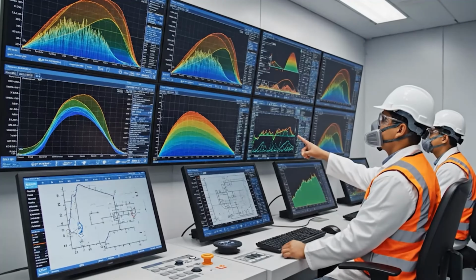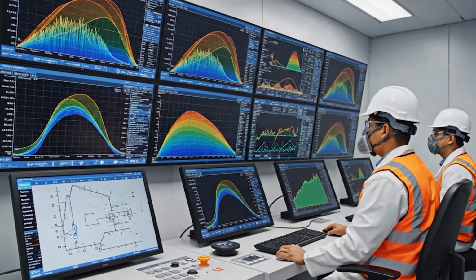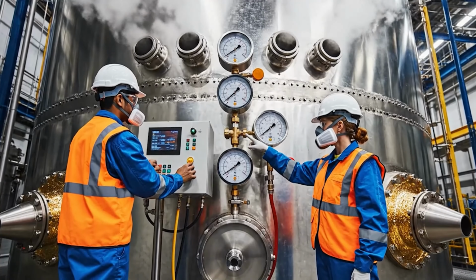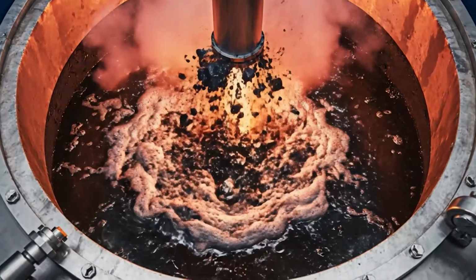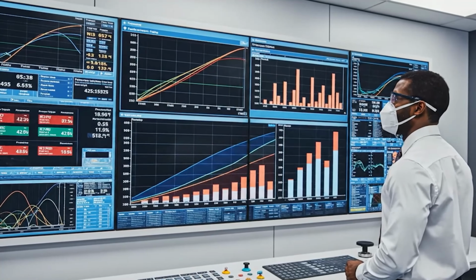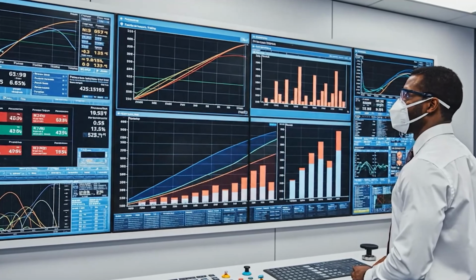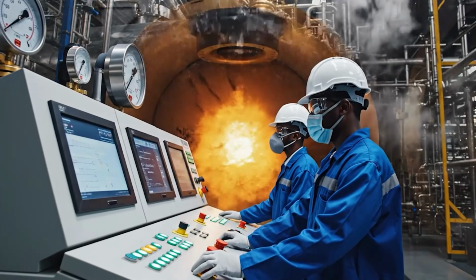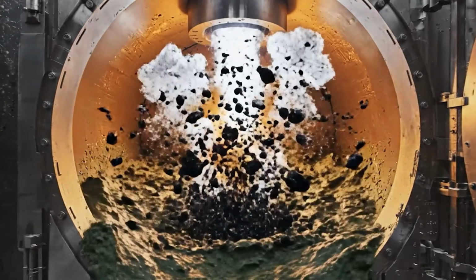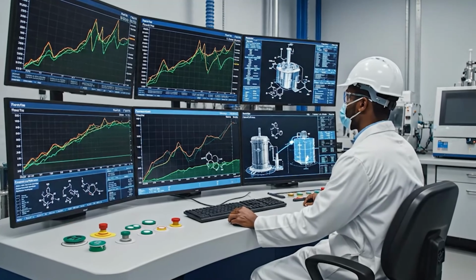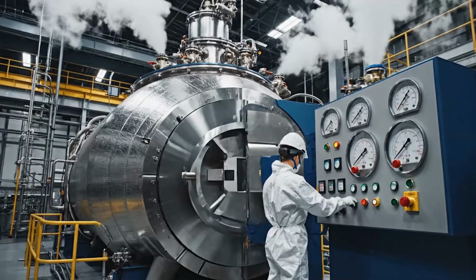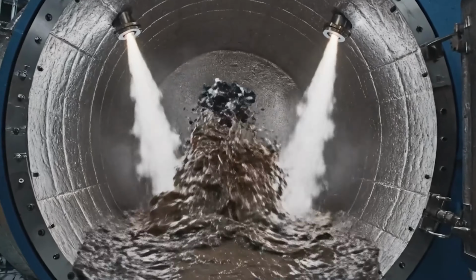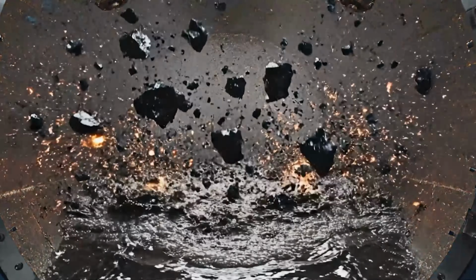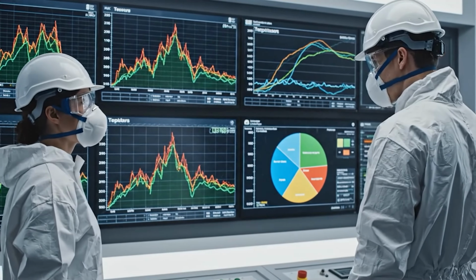Pressure oxidation, the modern solution. Concentrate is cooked in giant autoclaves. Think pressure cookers the size of buildings, at 200 to 225 degrees Celsius and 30 to 35 bar pressure with pure oxygen. Under these extreme conditions, sulfides oxidize in hours instead of requiring high-temperature roasting. The gold is liberated without atmospheric emissions.